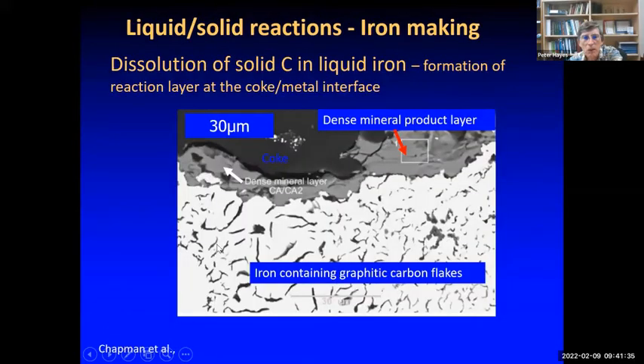So what's actually happening? Well, again, look at the interface. And we see that the coke here in the black is separated from the iron. And this is a solidified iron, graphitic gray iron. You can see the graphite flakes, carbon flakes in the iron. And in between the coke and the iron, which was liquid at temperature, we formed a dense layer of a mineral which contains calcium and alumina.